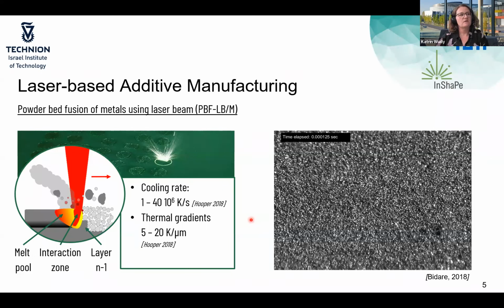The other process regime is where you create a so-called balling effect. I've mentioned it before, which means that due to surface tension mechanisms, you create some kind of balling elements on your melt pool, and this obviously may lead later on to defects in our component. And the last section would be if you have high process speeds and low laser powers, you see some kind of undermelting, so the weld depth is quite low and you're not able to melt one layer fully. The layer thickness is always around 40 and maybe 80 microns, and if you have a welding depth of less than 40 microns, you're not able to connect your layers with each other.